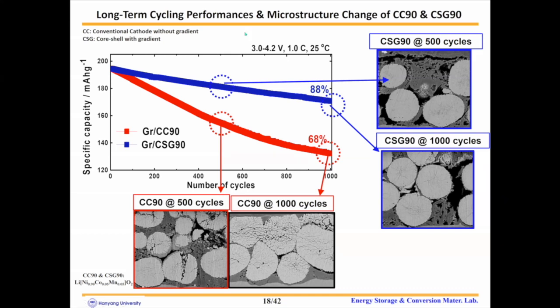the CC90 cathode. As you can see from the cross-sectional SEM image, after 500 cycles, microcracks and particle fracture were observed in the CC90 cathode. And furthermore, after 1,000 cycles, the CC90 secondary particles nearly pulverized into the individual primary particles. On the other hand, in the case of the CSG90 cathode, no visible microcrack was observed after 500 cycles, and only hairline microcracks were observed within the particle interior after 1,000 cycles.